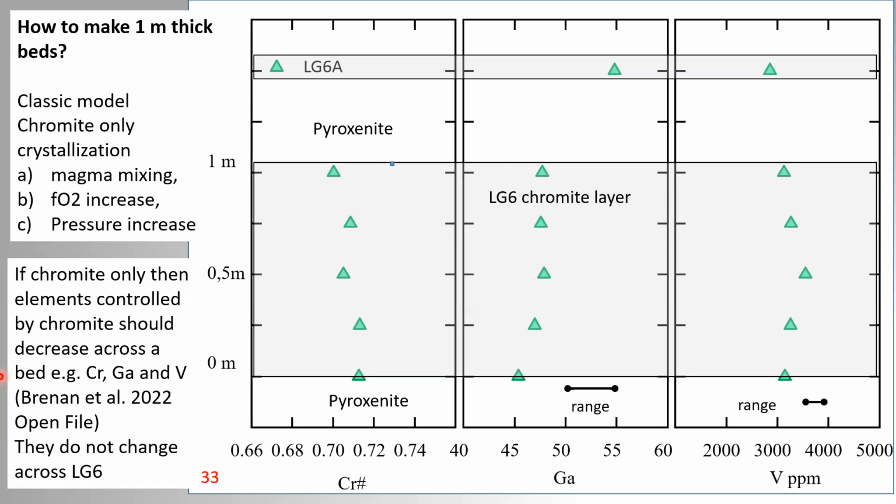Sorry, I wasn't quite clear there. The chromite in the Bushveld chills, the dikes that inject, the IPGEs do appear to be in the chromite. But in all the other chromites we looked at, whether they were disseminated or massive, we had no PGE. It was less than detection limit of PGEs in the chromite. So from this, it is inferred that the IPGEs rapidly form their own phases.